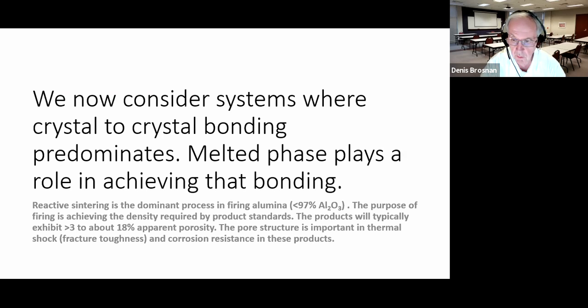Typically, the products that I talk about today are going to have about 18% porosity or less. Typically, 16% is very common for those. The pore size distribution becomes very important in improving thermal shock resistance or providing thermal shock resistance in these products. Another way of saying this, it improves the fracture toughness. Corrosion resistance, of course, is very important in a number of these products. Corrosion against liquid slags and things of this particular nature.